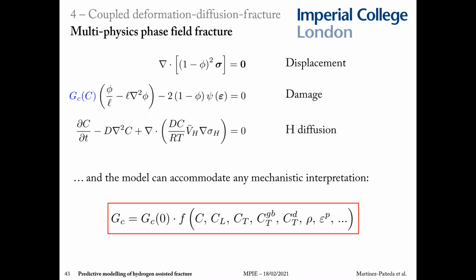The key idea is that you have a material toughness that, in the absence of hydrogen, we know very well. We can characterize it with a fracture experiment. And then in a hydrogen-containing environment, you can introduce what we call a degradation function, here called F, that can be dependent on any mechanistic parameter that you consider relevant.